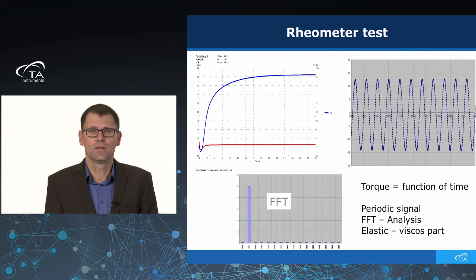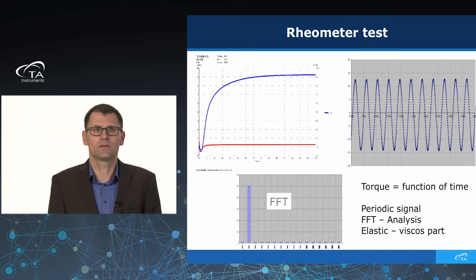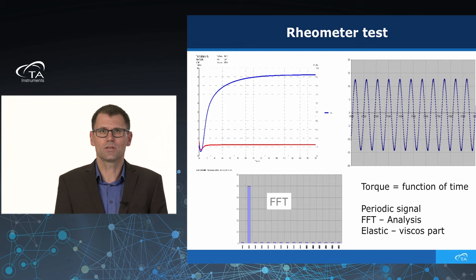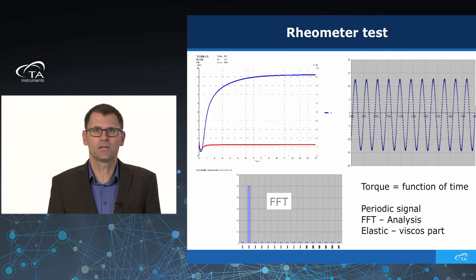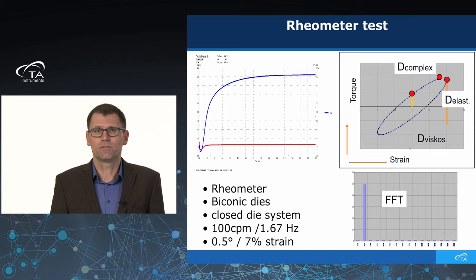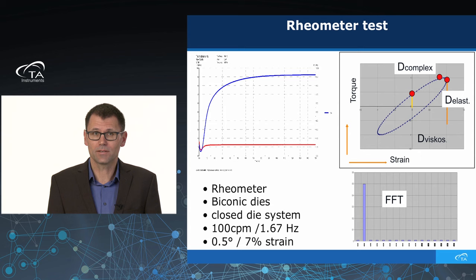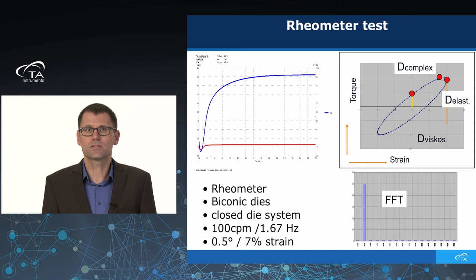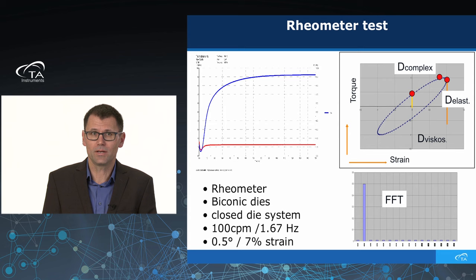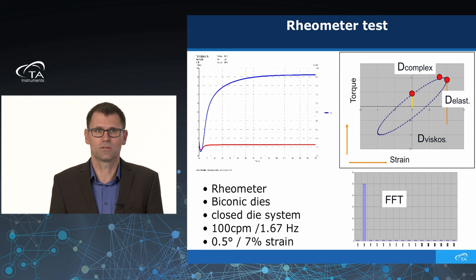If you plot the sine curve as a function of frequency, you get one signal in the Fourier transformation at one frequency, if you have an optimally linear and clean sine curve. Another way to calculate the elastic and viscous parts is directly from the ellipse: at the highest strain you get the elastic part, at the absolute highest value you get the complex part, and when the strain is zero you get the viscous part. Normally, we use the Fourier transformation to calculate G prime and G double prime.